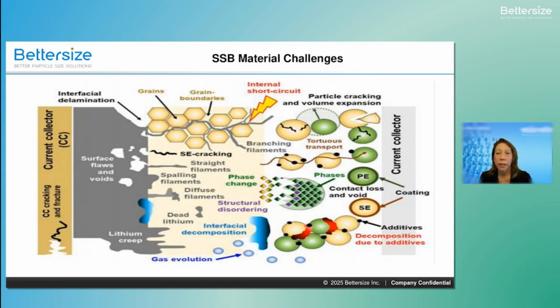Another key limitation is interface instability. Again, poor contact between electrolyte and electrodes can result due to the rigid materials being used. Chemical reactions at interfaces can lead to increased resistance and degradation. Lithium dendrite penetration through solid electrolytes can cause short circuits.